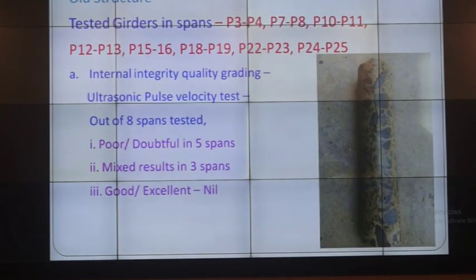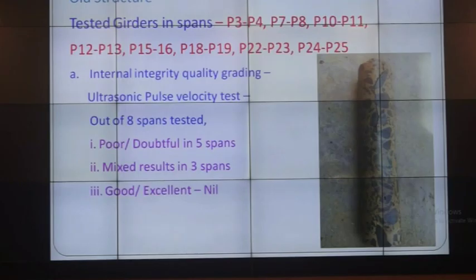Then we have checked the girders. These girders were poor, doubtful in 5 spans, mixed results in 3 spans, excellent results nil. There were no excellent results. And see, one of the girders, core along with the crack, when we removed the core, this is the type of core we got. You see the center crack there?